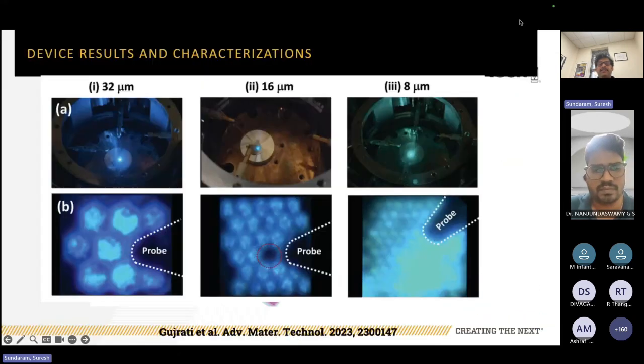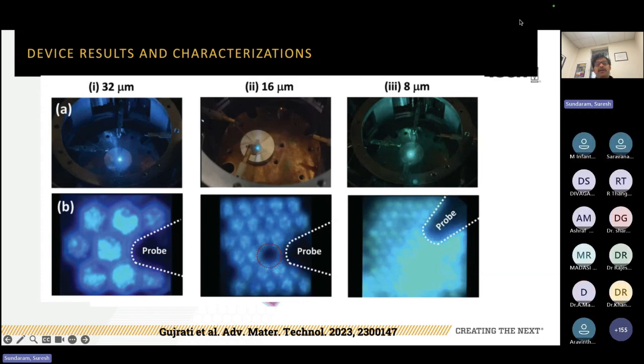So this is the device results. You can see that when you change the feature size or the opening size, you can go from 30 micron down to 1.4 micron. When you are at a 30 micron opening, you are getting 460 nanometer light.